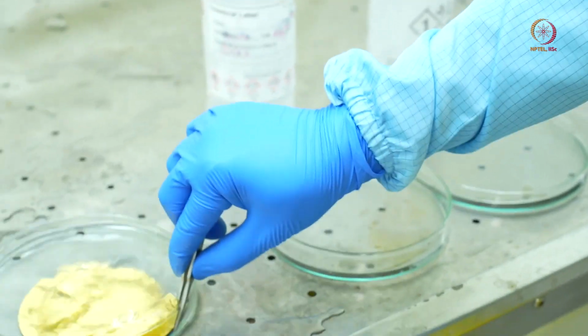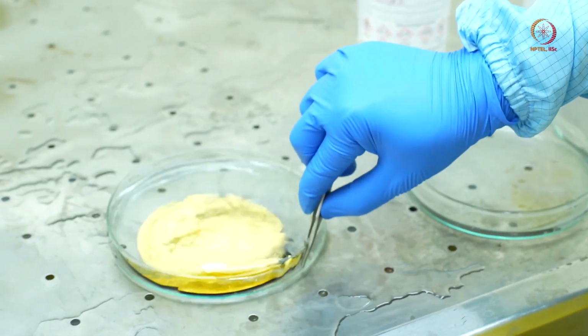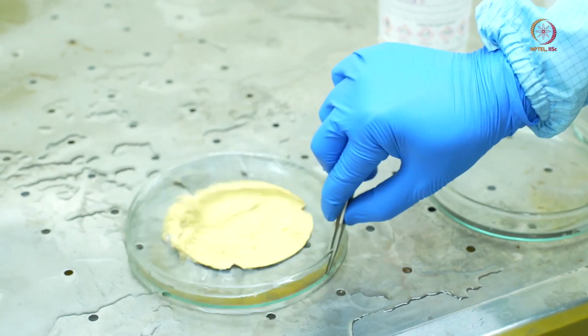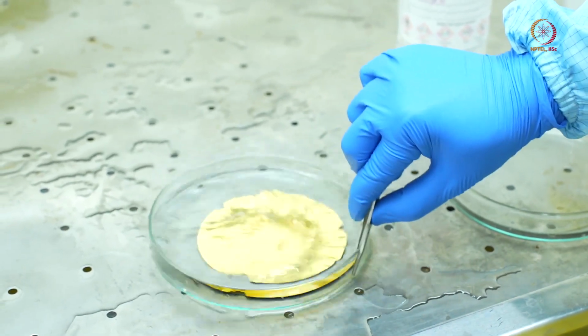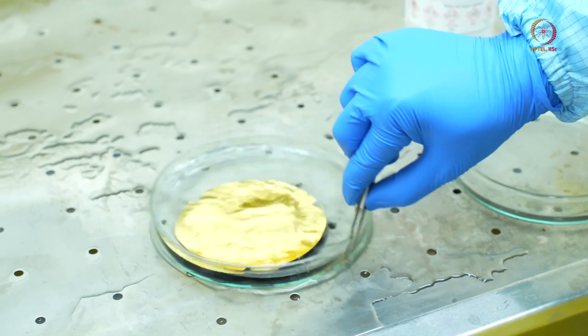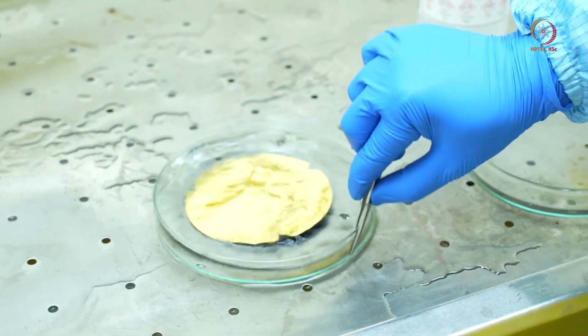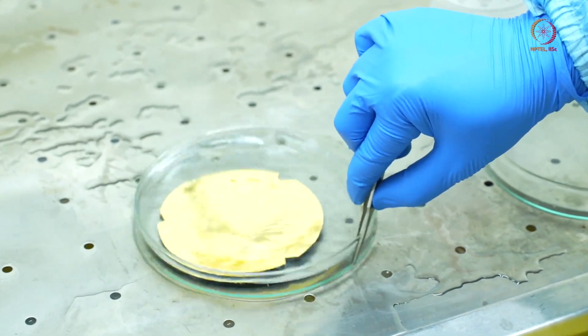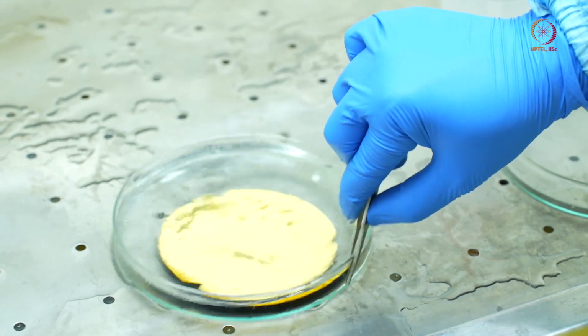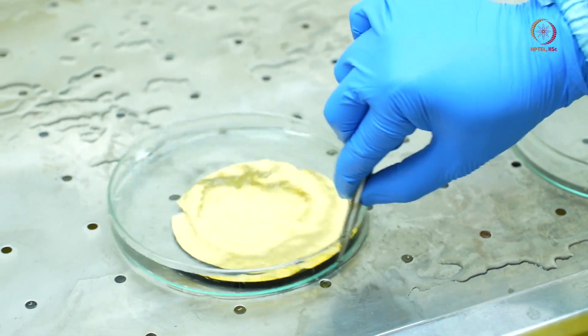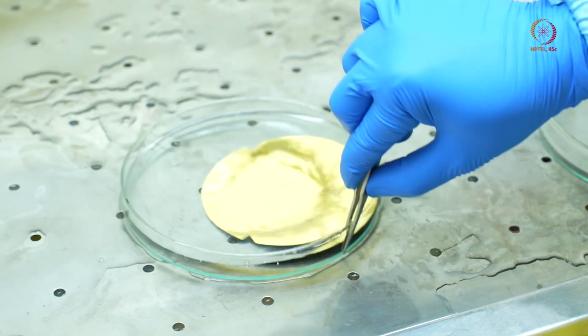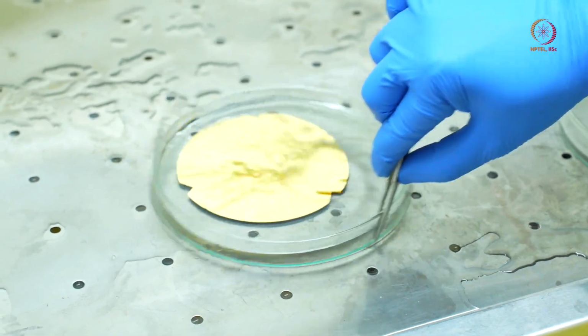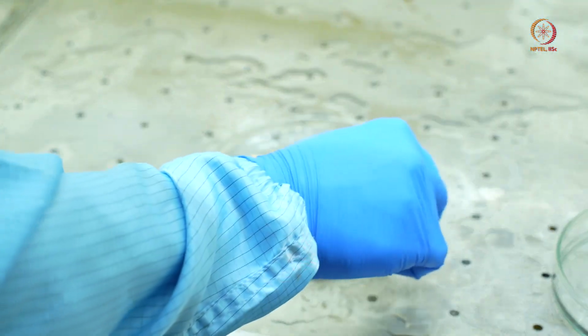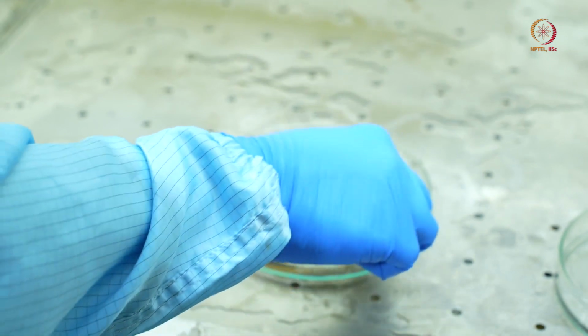So 5 minutes over. So I am removing the sample from IPA and moving into DI water. So now, basically acetone removes the contaminants. IPA makes sure the entire acetone is gone, and finally in the DI water clean, the DI water actually removes the entire IPA, so that we will have the clean wafer. So now we have finally cleaned it in DI water here, right?